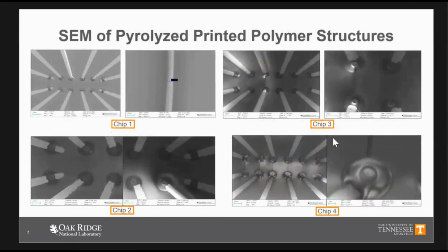So these are some of the samples that we have developed, and we have repeated that process with different laser power in the input, different percentage of laser dosage. As you can see in the SEM image, the initial size of the bridge was 4 micron in diameter, but it shrunk down to about 70 to 100 nanometers, which is a common phenomenon that whenever you are burning polymer or doing pyrolysis, it will be affected by shrinkage. So one of the samples here is developed with IP-Dip, and we have seen similar performance as compared to IP-S.